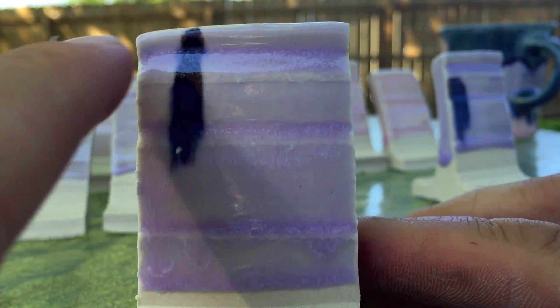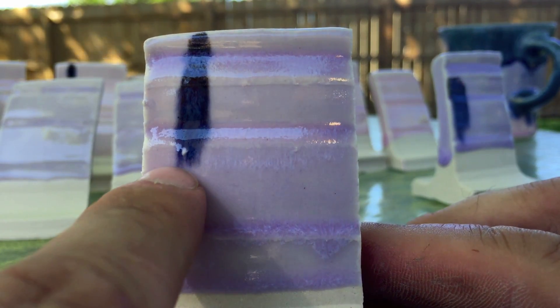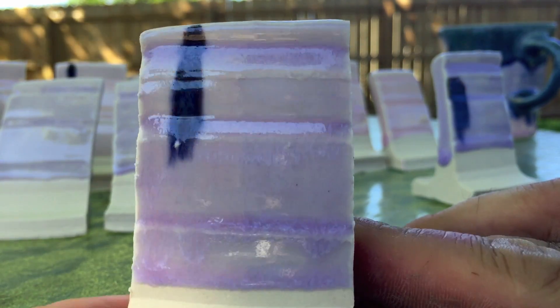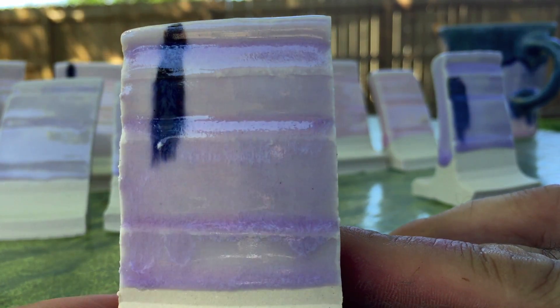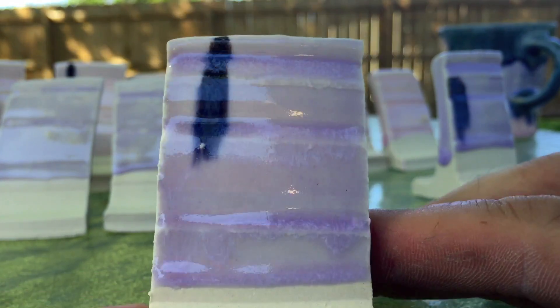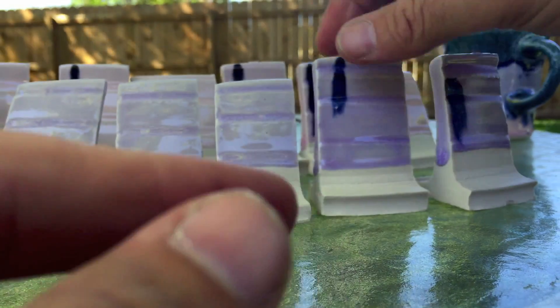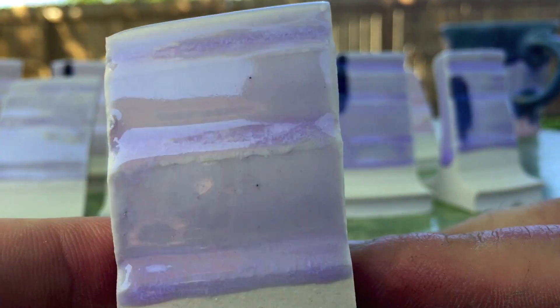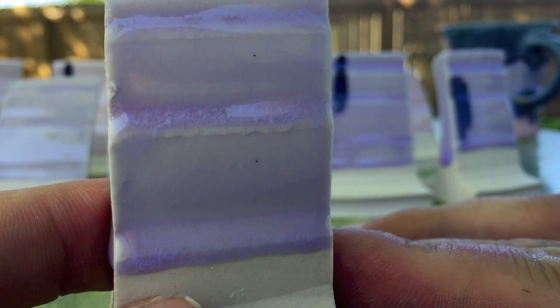You can see the purple is beautiful. And clearly it has pulled some of the black underglaze — it's an Amaco LUG 1 black underglaze. This is on Grolleg Kaolin Porcelain, Cone 6. Really nice surface, really beautiful glaze there. That is again 8%. At 7% it's pretty transparent — there's not a whole lot of crystals in it. Nice glaze.